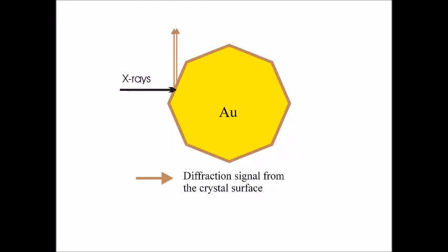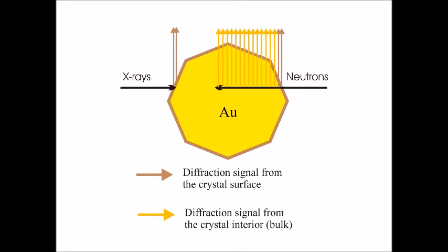To look at the crystallinity of materials, the standard methodology is X-ray diffraction. However, because gold is so dense, X-rays only penetrate the very surface. And if we want to look at the interior, we would typically have to cut samples like this open. However, because of the great value of specimens like the Ramshorn, we can't do that. Instead, we had to turn to a different technique. Instead of using X-rays to probe the crystallinity of our samples, we turned to neutrons. Neutrons are very penetrating and can go through an entire sample like the Ramshorn without having to cut it open.